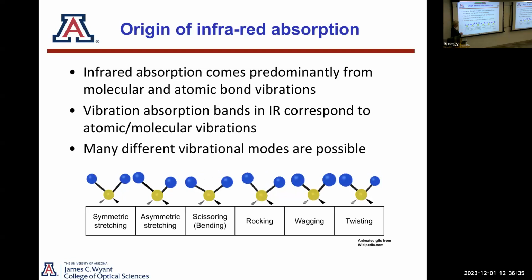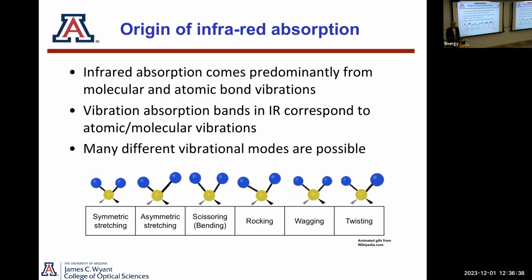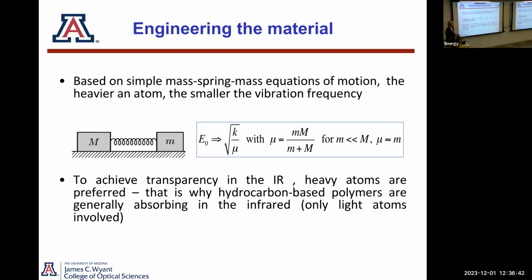This is a simple picture and animation that shows that. And what largely governs the frequencies at which these vibrations happen are the masses of the respective atoms, and other factors that affect the intensity of the absorption. But the positions of the frequencies are relatively easy to predict in a little bit beyond harmonic oscillator models. I just have a simple oscillator model here, but the important thing is to note that you care about this reduced mass, and that reduced mass becomes the mass of a small atom. If you have a small atom and a big atom, this basically becomes equal to the mass of the small atom, which makes this energy big, which makes you have absorption in the infrared at high energies.